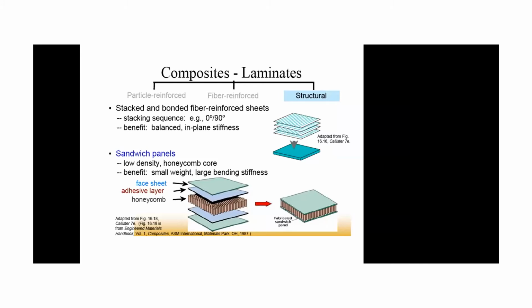And the third category is structural, where the reinforcement and the matrix are of same size. It is not like that in the other cases, where the reinforcement is a very small particle, or in case of fiber, a long thing. But in case of structural, both are more or less same size. So as you can see in the case of stacked and bonded fiber reinforced sheets, so one is the fiber layer, fiber sheet. Means you are using fiber sheet instead of single fiber. So one layer can be fiber reinforced sheet, another can be polymer. So they stack together in each other, and then hot press or other way we are making the component.